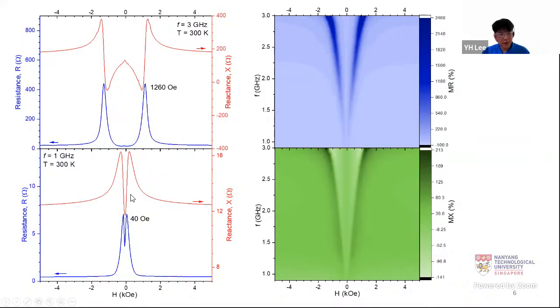At a similar critical field value, we can see that the reactance shows a sharp peak followed by a rapid dip at the same values. Similar features are also seen at 3 gigahertz. However, you see that there's a rapid peak and dip.